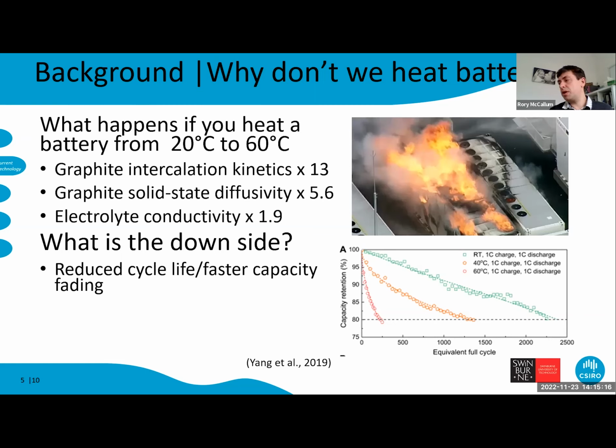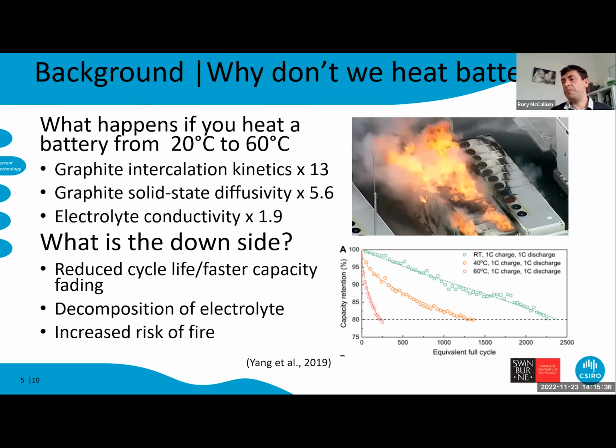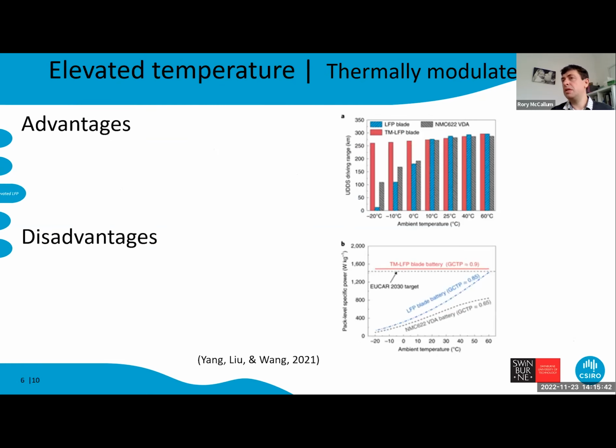It also means that we go from around 2000 cycles, if we charge it at 1 hour charge, 1 hour discharge, to around 250. And this is because of the growth of chemical reactions at the anode and the SEI layer, or the protective layer of the anode, and just ultimately decomposition of the electrolyte. And this also increases fire risk. So there's some big issues.